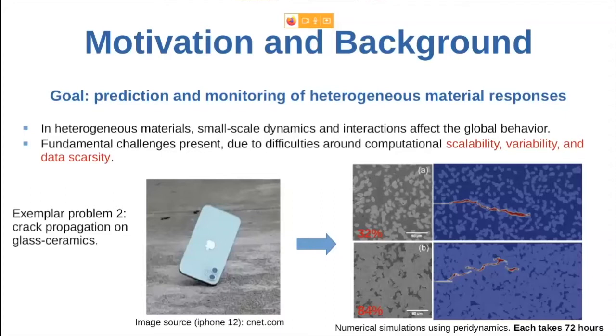So if you're interested in, for example, designing a better glass ceramics material, then I need to study this crack pattern for different microstructures. That becomes really non-feasible, because each simulation needs to resolve all these small structures, and that takes a really long time, like 72 hours in this particular problem, to simulate one microstructure.